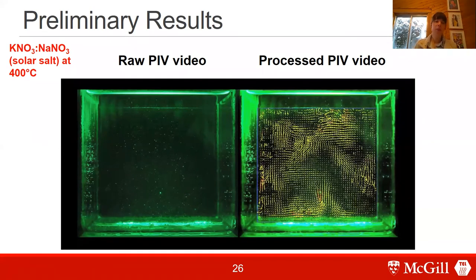So these are just preliminary results that we produced in our lab, and we're continuing our work to reproduce these experiments at higher temperatures in molten salts that are used in actual molten salt reactors and under typical reactor conditions, and then developing new heat transfer correlations for convection in molten salts with thermal radiation.